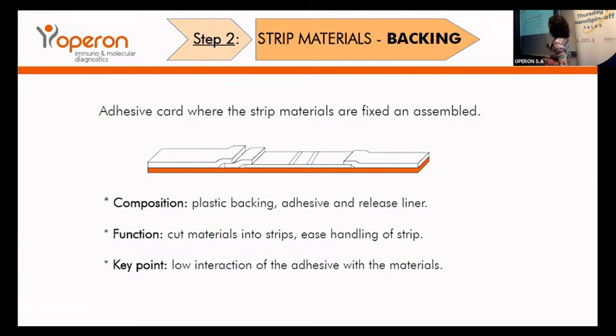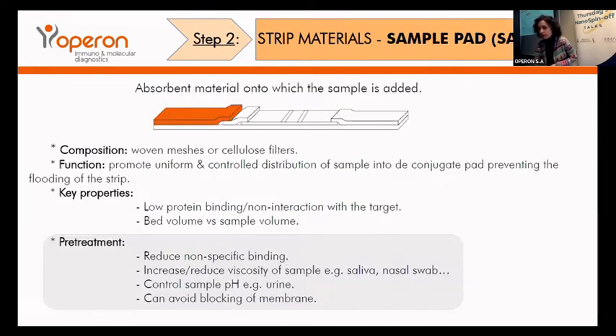The main concern is the adhesive, because we really don't want it to interact with the materials of the strip and change their properties. As we commented before, the sample pad is an absorbent material where we are going to add the sample. It is made of woven meshes or cellulose fibers that promote a uniform and controlled distribution of the sample into the conjugate release pad material, and also prevent flooding of the strip.